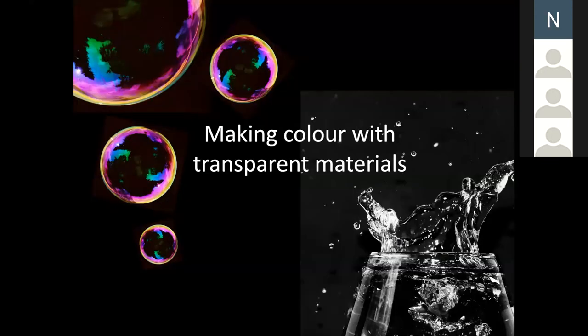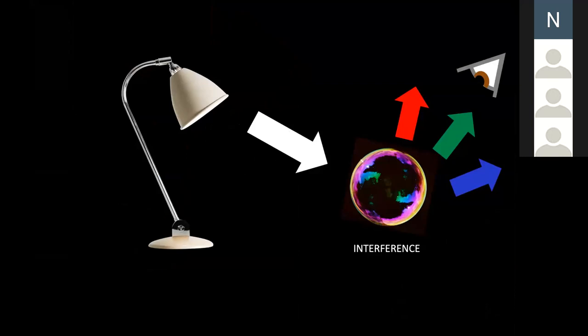In contrast, you can obtain different colors by structuring transparent material. This sounds weird, but if you think about a soap bubble, water by itself is a transparent material. But as soon as you create this structure, this few hundred nanometer layer, you are able to interact with light with a phenomenon that is called interference, and then obtain this color out of a non-absorbing material. And since the mechanism is different, the characteristic of the color that you obtain is also peculiar. Depending on the direction that you observe the object, the color changes, and this effect is called iridescence. This is typical of structural color.